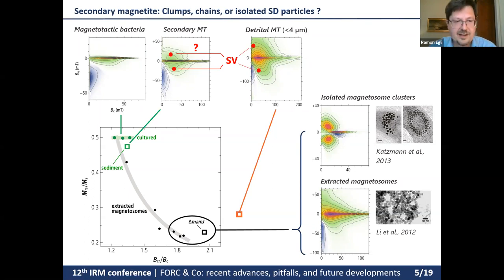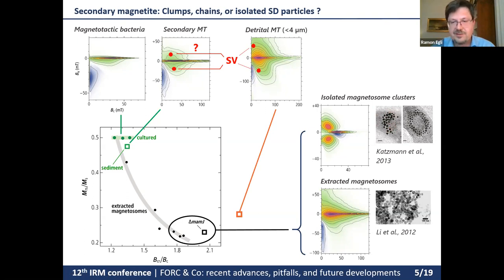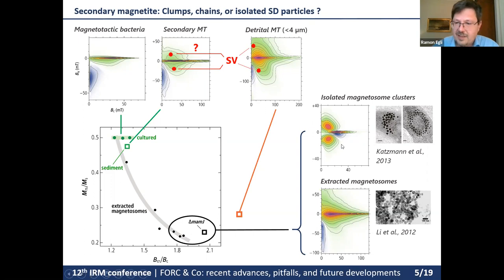Of course these are not single vortex particles — they are too small to host a magnetic vortex. What is seen here is a super-vortex: a flux closure arrangement of magnetic moments that eliminates the stray field. Nevertheless, the FORC signature is very similar to that of completely different particles.